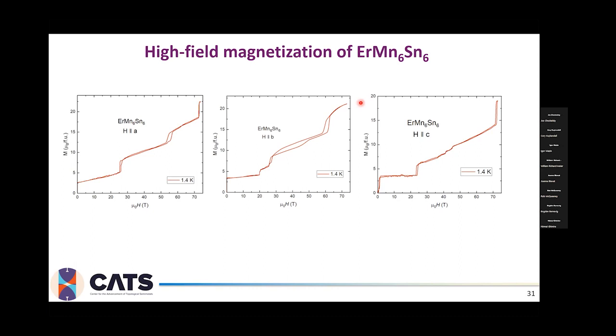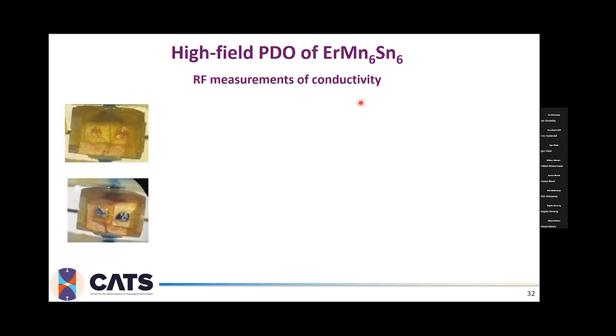So with those data, when we are able to more or less collect the information about all the magnetic phases in that material, we wanted to look at how it may influence the transport data, conductivity, and if we will see any sign of non-trivial topology. So we started by measuring the PDO, which is a radio frequency measurement of the conductivity.